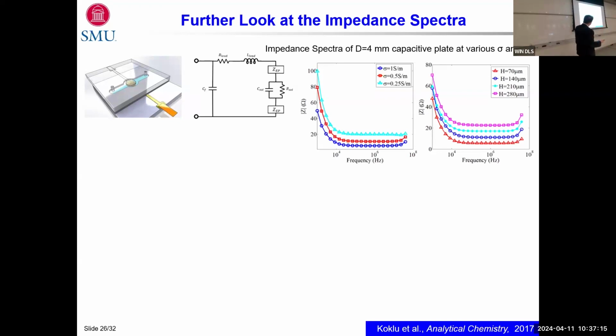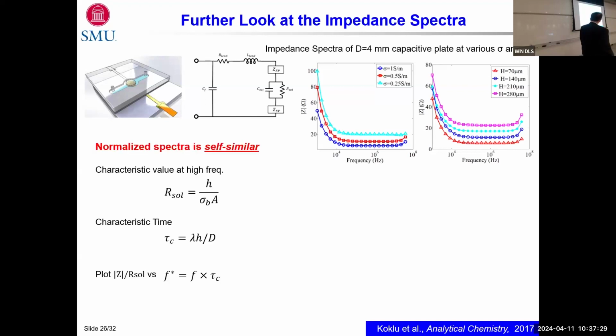Well, you make a bunch of experiments, and then you see these figures. These figures look very similar to each other, right? So there must be a way that I can put them all on top of each other, because I'm a fluid dynamicist, and we like non-dimensionalization of things, right? So basically, if you see that the high frequency range is reaching the solution resistance, you can normalize the impedance with the solution value, and that becomes a normalized value. And then perhaps you can actually come up with a characteristic time scale that's going to normalize your frequency.